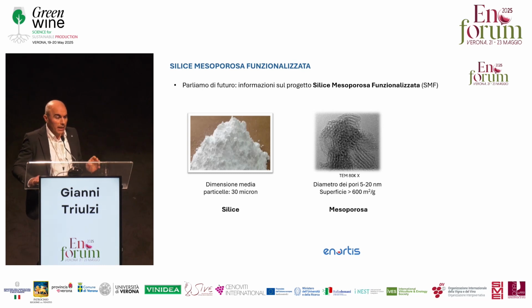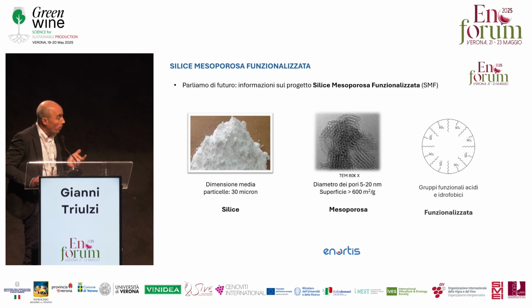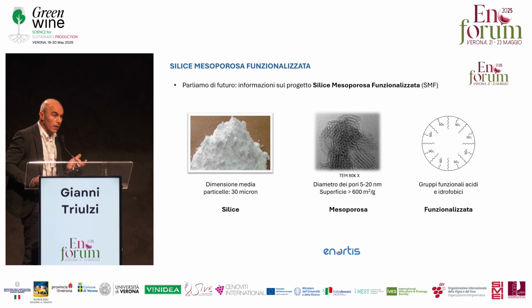This special structure entails that there is an incredible surface in the material. In that, if you read, 1 gram of the material has an active surface exceeding 600 square meters. I say active surface because functions are present on that surface.